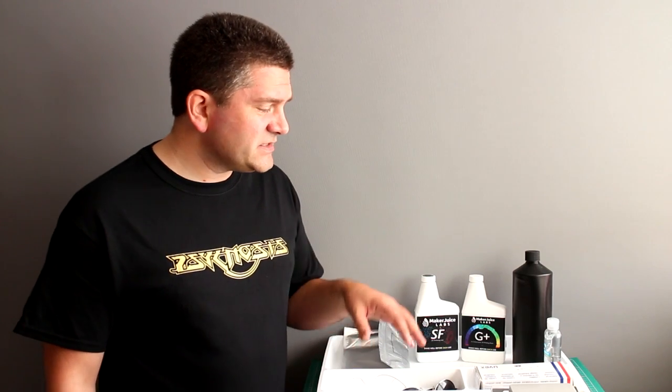The other side of things is UV and ultraviolet light is what we're going to be using to cure the resins. All of these resins cure with ultraviolet light from around 365 nanometers up to about 410 nanometers. Traditionally we've used normal DLP projectors and they're okay. They have a wide spectrum of light that can transmit some UV but you've got to use a hell of a lot of light, so 180 watt bulb just to get a small amount of UV to come through and cure the resin.